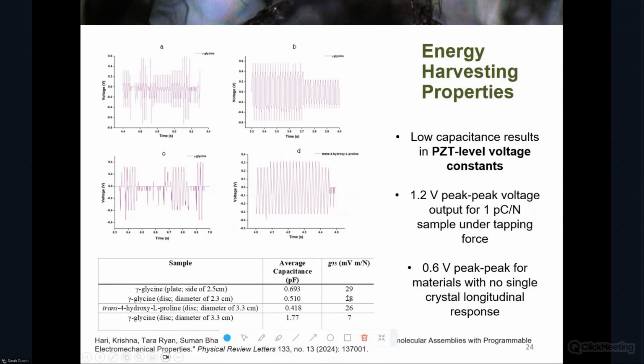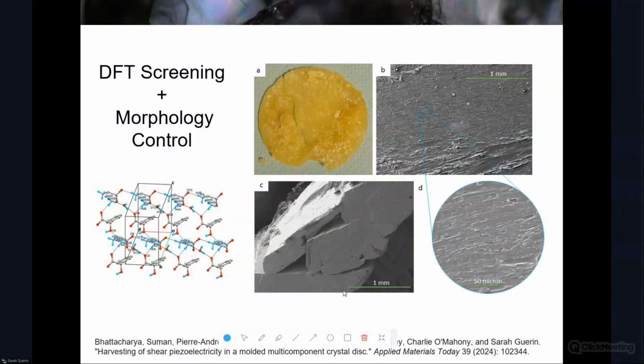And where we get then is we have our DFT screening, where we can identify interesting candidates with high properties. We have our growth processes, where we can grow these as these macro scale rigid polycrystalline assemblies. And now we have our device and application testing, where we can move them forward for our energy harvesting testing. So this is an example led by Suman Bhattacharya, who's a postdoc in my group, where he discovered this mandelic acid lysine co-crystal that had that longitudinal piezoelectricity that I mentioned before. And that, again, we were able to mold into this macro scale disc.